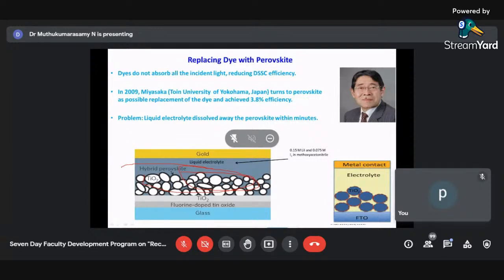But one important thing which he was able to understand was that particular solar cell didn't last long. Only for a few minutes he got an efficiency of 3.8%. After that, that liquid electrolyte completely ate away the perovskite material. The entire perovskite was dissolved in the liquid electrolyte within a few minutes, and the efficiency dropped down to 0. So the lithium iodide electrolyte which he used, and the methoxyacetonitrile, all those things completely ate away the perovskite material. So the cell had a lifetime of only a few minutes.